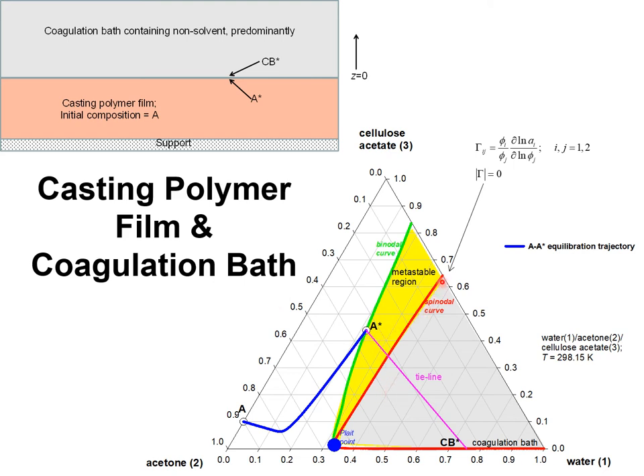The spinodal curve is defined by this expression here, determinant of gamma equal to zero, where gamma is a matrix of thermodynamic correction factors that can be determined using the Flory-Huggins description of phase equilibrium.